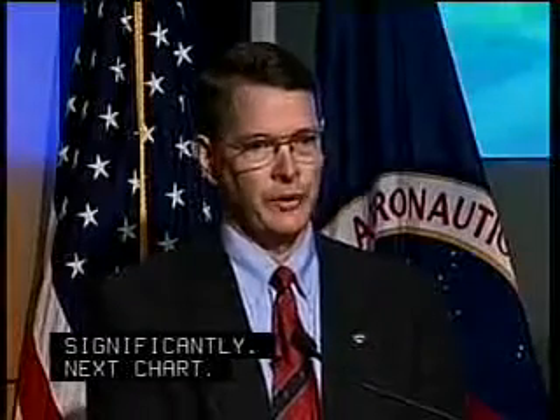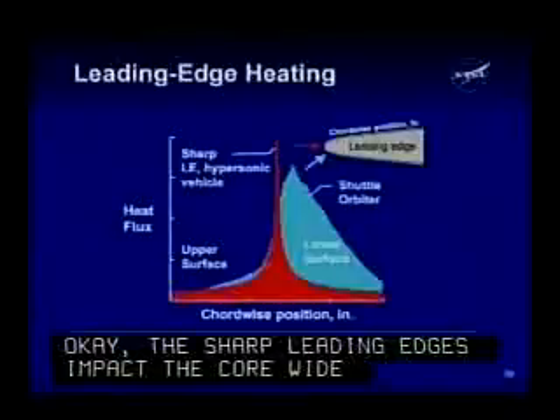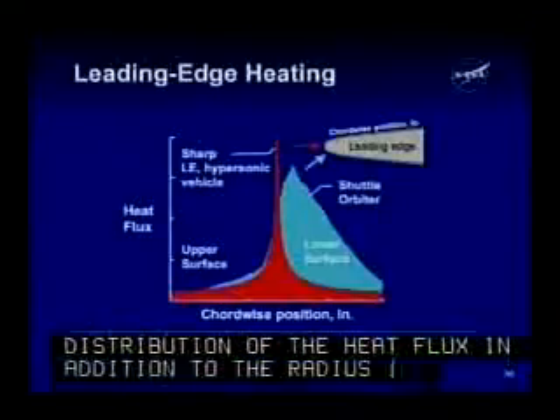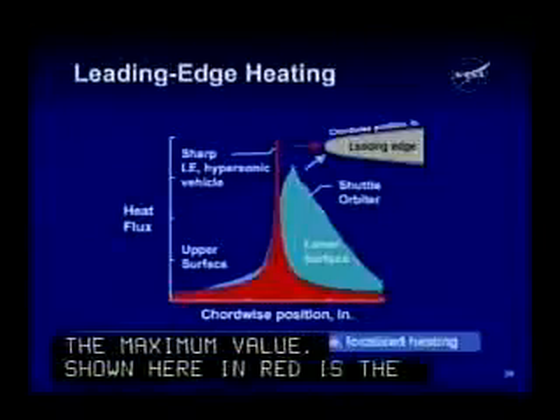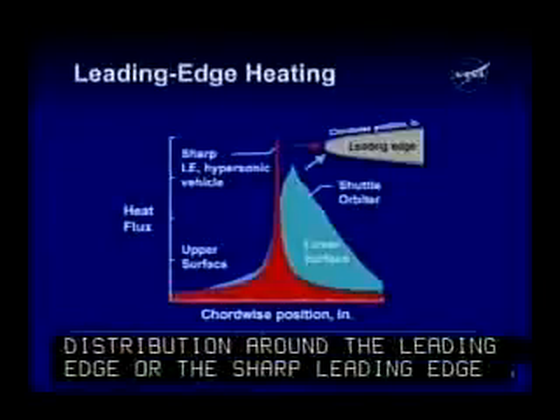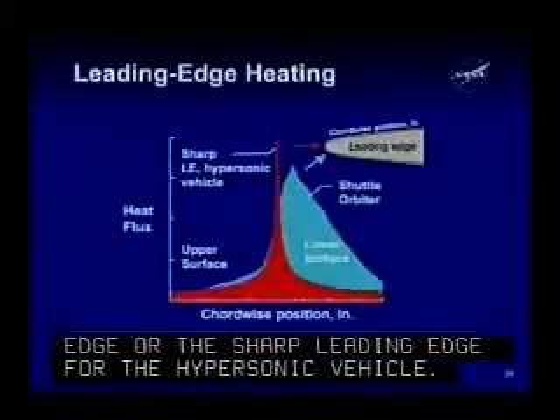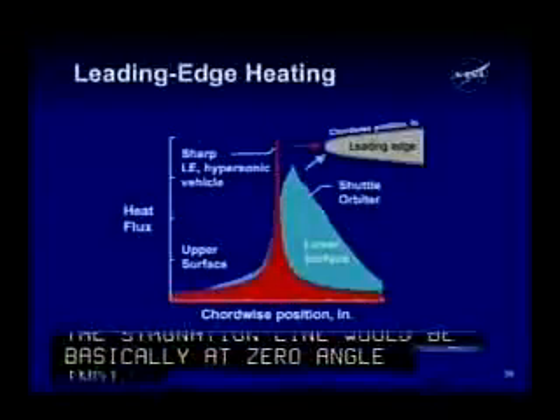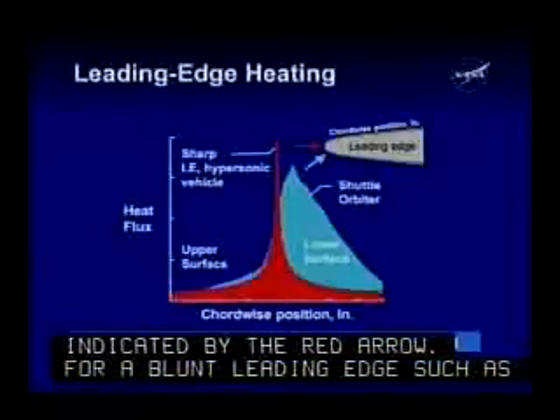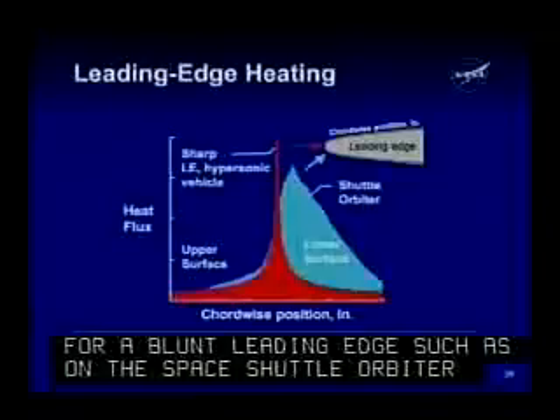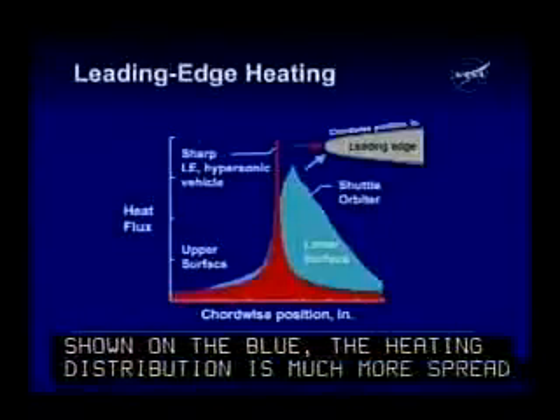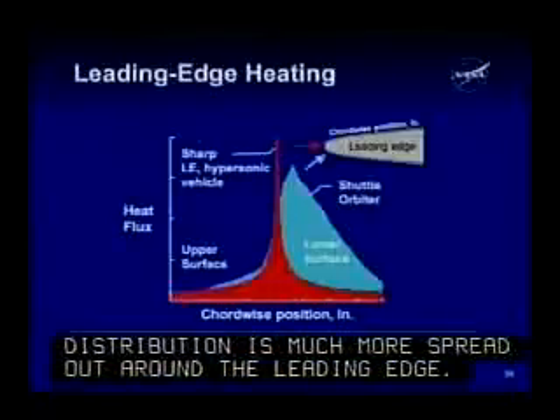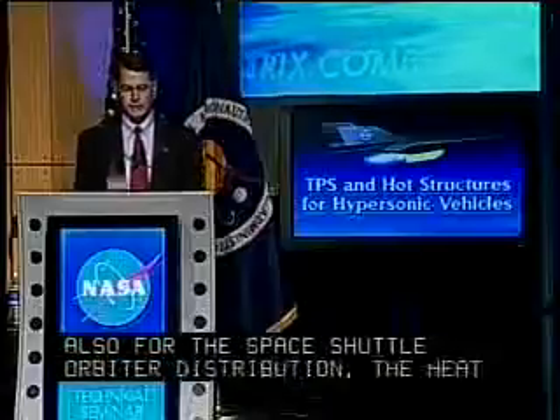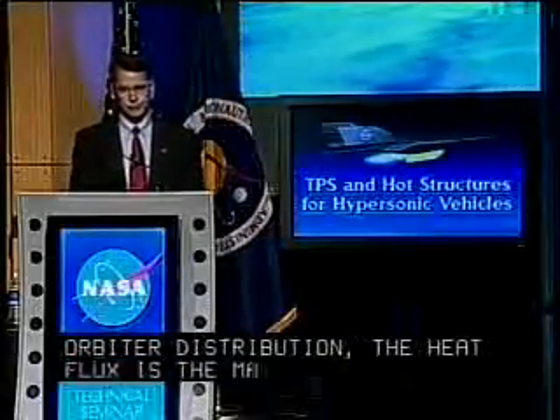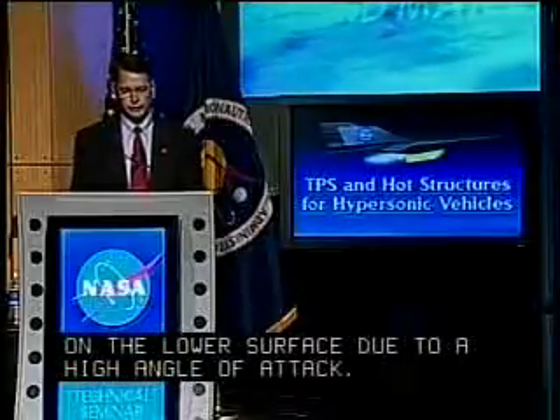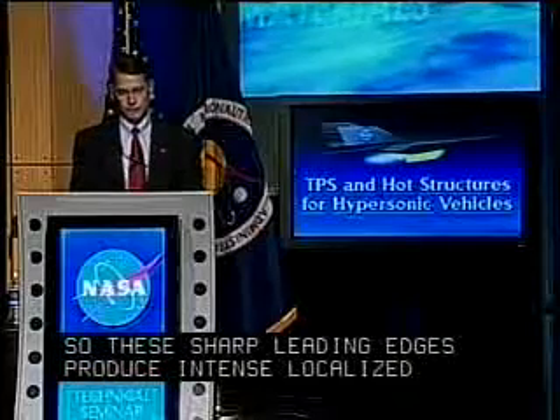Okay, the sharp leading edges also impact the chord-wise distribution of the heat flux, in addition to the radius impacting the maximum value. Shown here in red is the distribution around the leading edge for a sharp leading edge for a hypersonic vehicle. The stagnation line would be basically at zero angle of attack, indicated by the red arrow. For a blunt leading edge, such as on the Space Shuttle Orbiter, shown in the blue, the heating distribution is much more spread out around the leading edge. Also, for the Space Shuttle Orbiter distribution, the maximum heat flux is on the lower surface due to a high angle of attack. So these sharp leading edges produce intense, localized heating. Next chart, please.